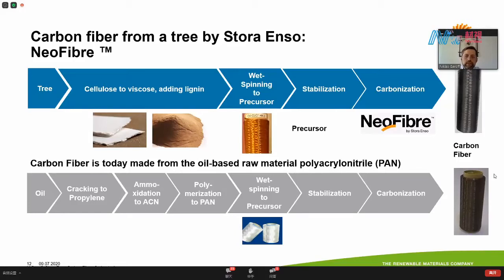And what you get is a white reel, as you can see in this bottom picture. And this precursor reel is then thermally converted to carbon fiber by feeding it to different furnaces at different temperature zones and different residence times. The first furnace is a stabilization furnace, where the precursor is converted from a thermoplastic material to a thermoset material. And then what follows is low temperature and high temperature carbonization. And finally, a sizing is applied, and then the carbon fiber is spooled and packaged. So, 98% of all carbon fibers today are made according to this process.